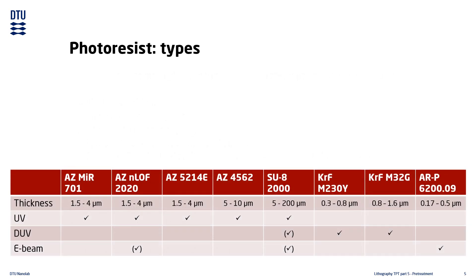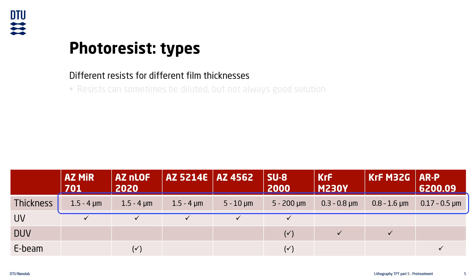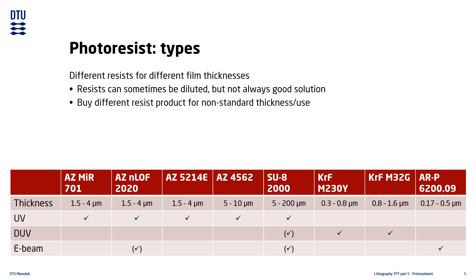There are many different types of photoresist products, and each is designed to produce a specific film thickness. It is sometimes possible to dilute a resist in order to get a thinner film thickness, but a diluted resist does not always produce the same quality film as the undiluted would have. It is also not possible to concentrate a resist in order to get a thicker resist film. The best results are often achieved by using the correct resist product for a specific process. At DTU Nanolab we have a wide range of standard resists available to users, covering a wide range of film thicknesses. However, the standard selection does not always suit every project, and users sometimes have to buy special resists better suited for their own projects.